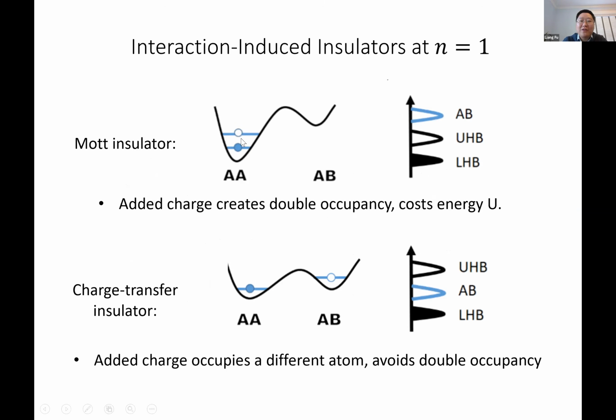And then two types of insulating states have been discussed in the literature, long before. In both cases the charges are in the anion sites, but they are distinct, and they are called the Mott insulator versus the charge transfer insulator. They are different from each other when we consider the excitations. What happens if we add an extra charge into the system? In the case of Mott insulators, it appears when the other site, the cation sites, has a much higher energy. So when an extra charge is added, this charge prefers to go to the AA site to form a double occupancy. This added charge creates double occupancy, which costs energy U, while occupying the cation sites costs an even larger energy.